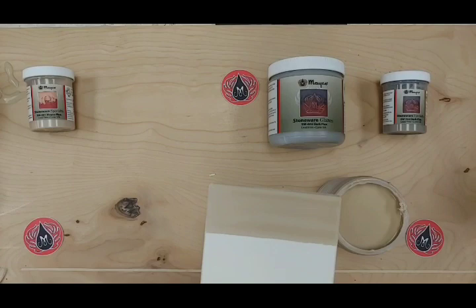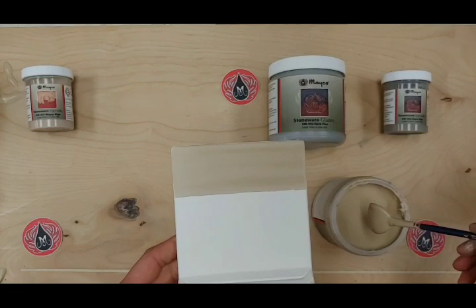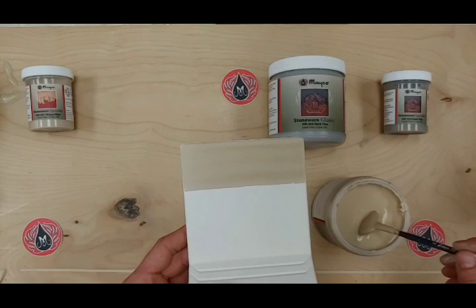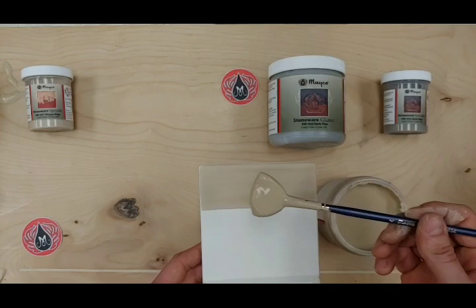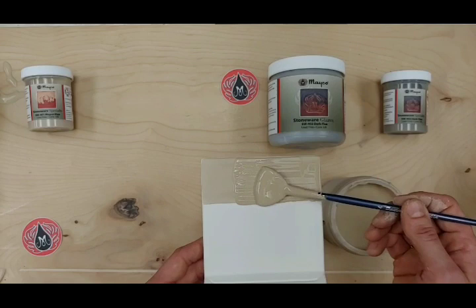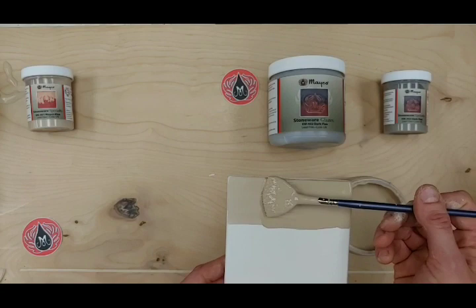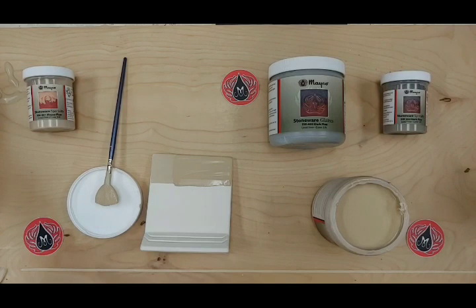This looks like it's dry now — it's not all the way bone dry, but it's not shiny at all anymore, so that's how I know it's time to put the next coat on. I'm going to stagger these coats so when I post the fired picture, you can see one, two, and three coats and what kind of mobility is produced. Loading up my fan brush again — it's fully plumped, the glaze isn't trailing off but it's definitely heavy. Second coat going on nice and super smooth. I'll do the same with the dark Flux and fire both tiles with the amber quartz, then post the images of light Flux and dark Flux results tomorrow.